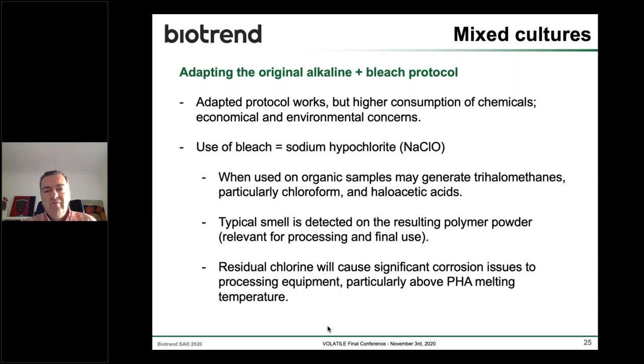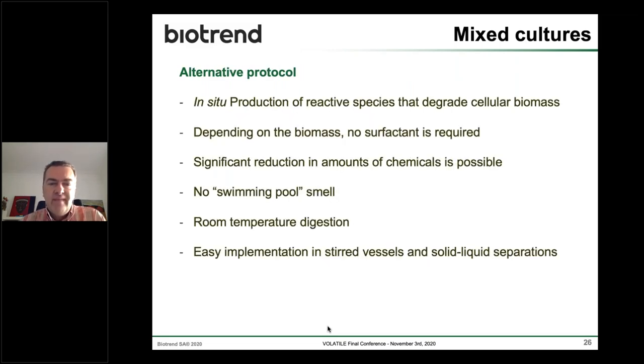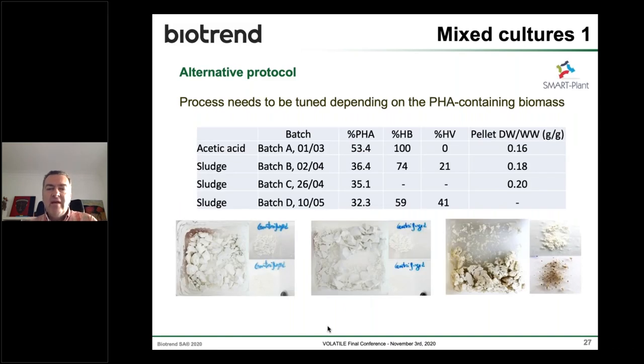So we wanted to move away from this, and we developed at Biotrend a protocol which generates in situ reactive species that degrade cellular biomass. And we were able to significantly reduce the amount of chemicals and got rid of this swimming pool smell. And we can do a room temperature digestion of the biomass and implement the process quite easily in stirred vessels and using solid-liquid applications.